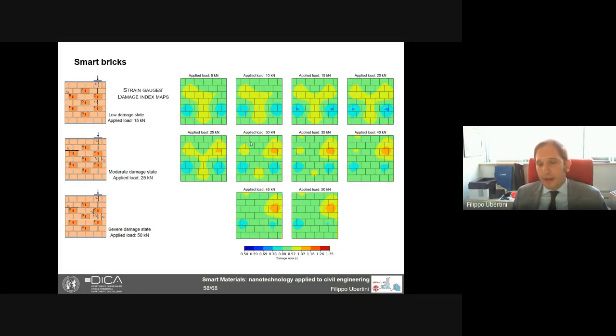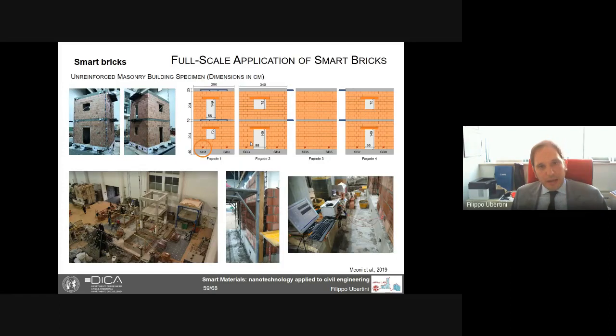If we do the same with the strain gauges, the location of the damage is much more challenging, and perhaps only at 25 kilonewton we can say that something is going on in the region where we have cracks C2, C1, and C4. Another interesting experiment, which I will go through quickly, was on this building,